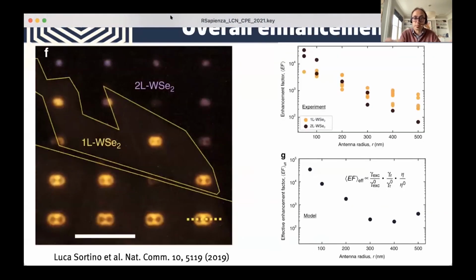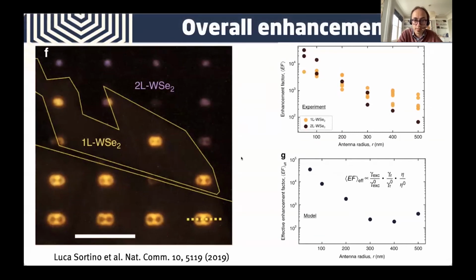And then of course, if you put it all together, this is the summary here on the bottom curve. You see this is the summary of all the enhancements that we get: the excitation, local density of states, which is quantum yield, and collection. You see that we can get to an enhancement of the order of 4 or 5 orders of magnitude, which depends, of course, on the size of the antenna that we're using. And on the top, you see the same enhancement, now experimental. There's clearly a spread, and this is a log scale, but you see that the trend is similar, and we do get very large enhancements.